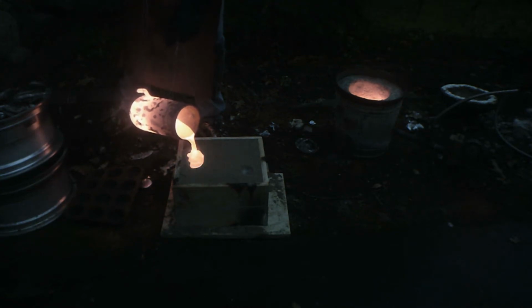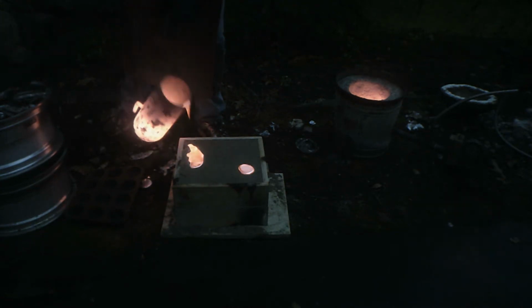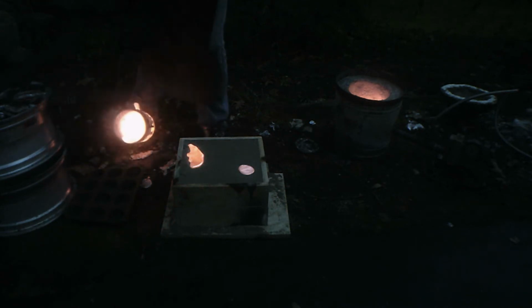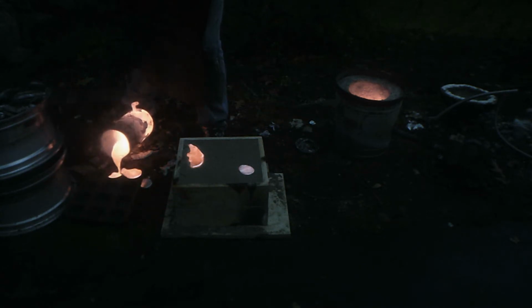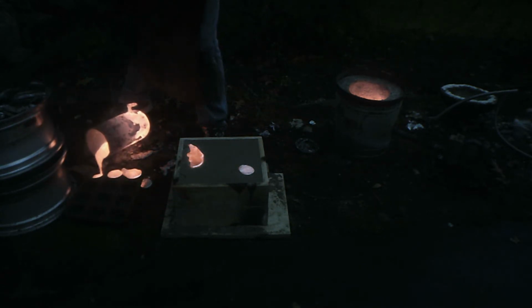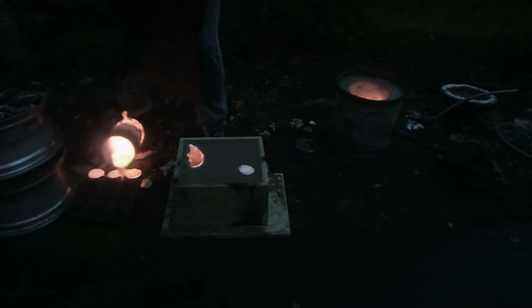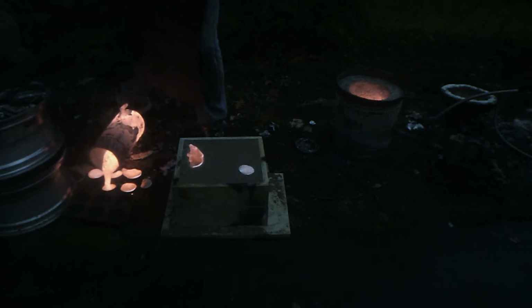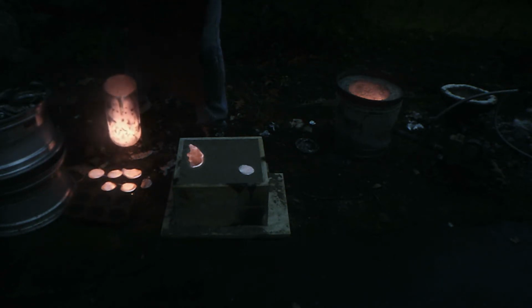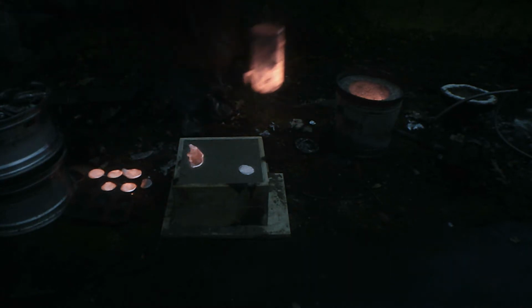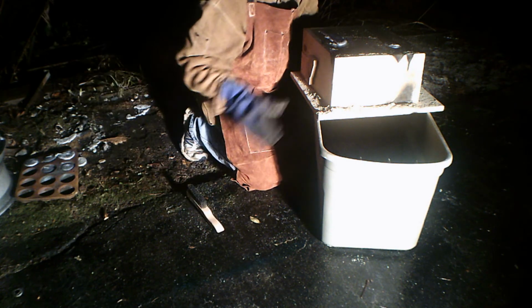All joking aside, the serious part here is making sure that the sprue is continually filled to the brim with metal for the entire duration of the pour until you see it coming up the riser. Now, you do not want anything to cool in the crucible, so any remaining metal has to be poured out. I'm using a muffin tin as an ingot mold so that it can be in little manageable sizes. And then just to cool off safely, I'm going to put the crucible back into the foundry furnace. And about 15 minutes later, we are ready to shake out the casting and see what's inside.